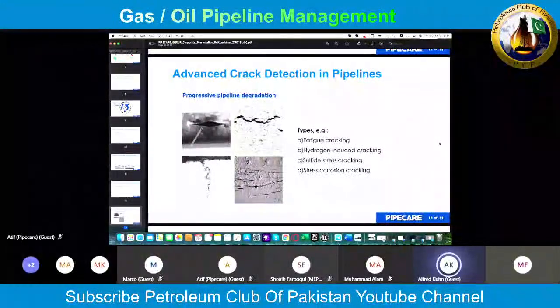What kind of cracks do we have? Cracks are normally not in the pipeline right from the start. And we can have fatigue cracking, which is a little bit outstanding compared to all other crack types, because fatigue cracking is happening when the metal is repeatedly stressed. So it's very easy to explain what fatigue cracking is.